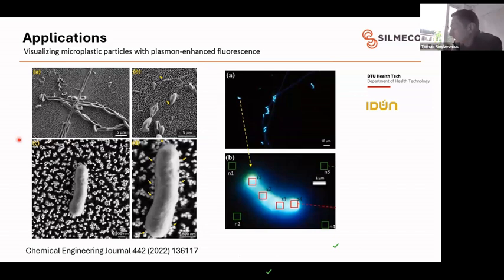And another example that we work on with some of the Swedish partners is using this plasmon-enhanced fluorescence. It turns out that these nanopillar structures can also enhance fluorescence quite effectively. And they were, and still are, interested in detecting microplastics in water. They collect different samples from lakes, rivers, and so on in Sweden, and then try to see if they can see traces of microplastic. And this was one way to do it. It turned out to be quite effective. They are now also taking it to the next step and working on a project where they are trying to use this method to detect microplastics emitted by 3D printers because they think it's a problem, at least in Sweden. So we hope that it will work equally as well as with detecting it from water someday.